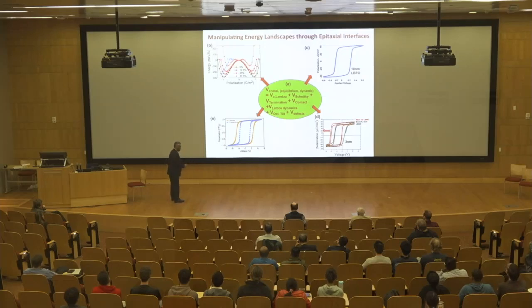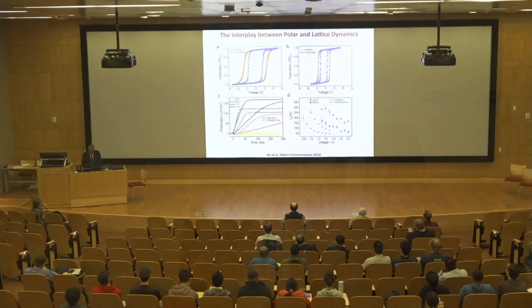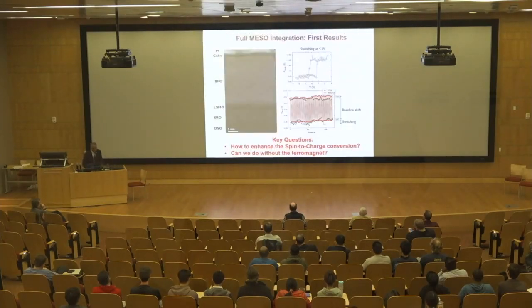The released sample is switching a lot more easily because the lattice plays a big role. Interfaces play a big role. That's what this is saying. I can tune my interface electronic structure by putting in additional layers. Just a couple of unit cells of different materials can tune all of this. Okay. Let me skip through some of these because I think there's too much detail. What we did was then to build the full device that Intel wanted us to build. And this took us, again, a few years.